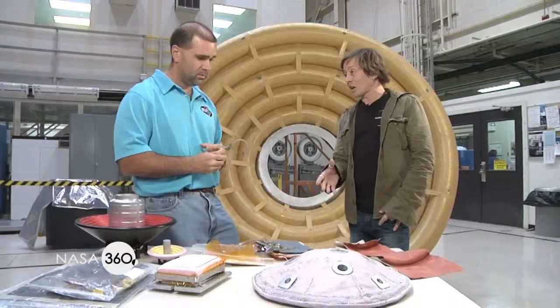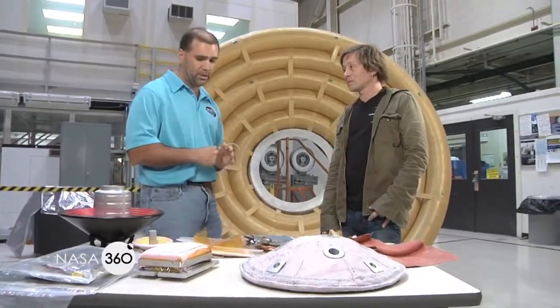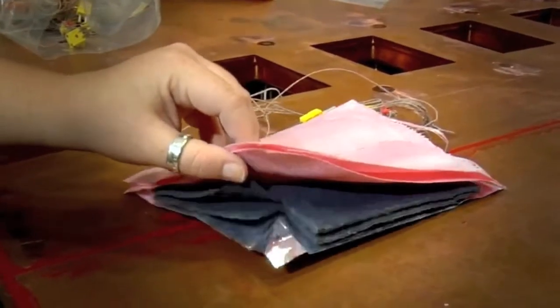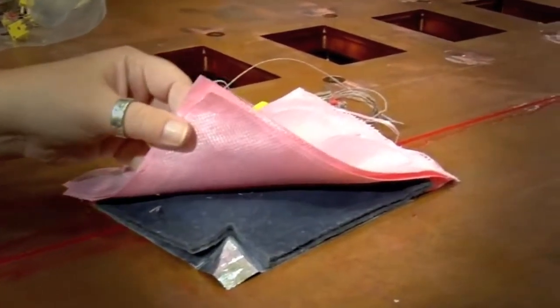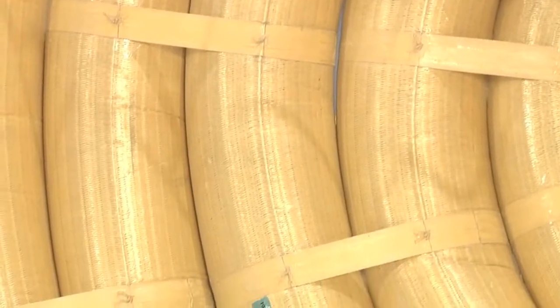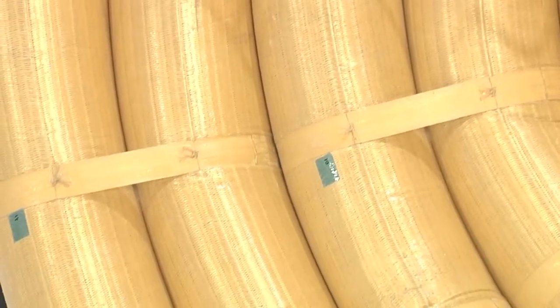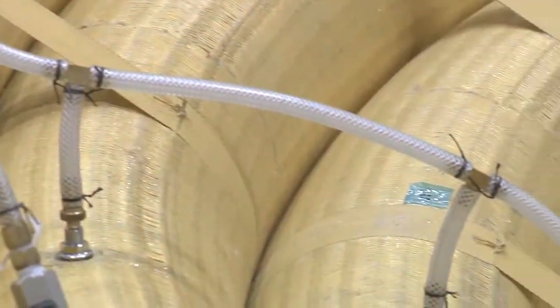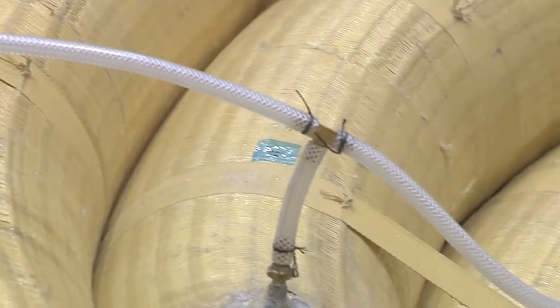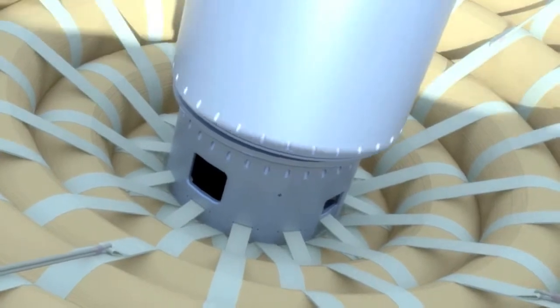The insulator is not very strong, and that is why we've included a Kevlar material inside the gas barrier. Now the inflatable structure itself is incredibly strong — it's a Kevlar braid. We braid these tubes up, then insert a silicone sheet rubber sleeve. That sheet rubber sleeve keeps the gas inside and tensions all of the Kevlar fibers. When you inflate it to about 12 to 15 PSI and thump it, it sounds like you're hitting a piece of metal. So it's pretty strong.